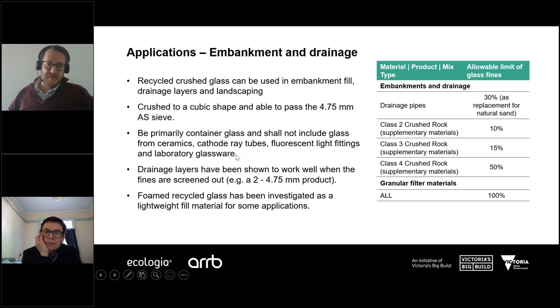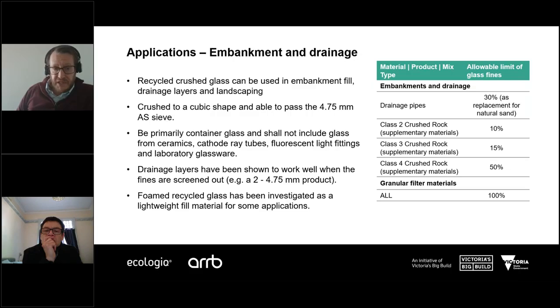Again, we need to be mindful of the source of our glass product. So we don't want to include any glass from ceramics or cathode ray tubes or fluorescent light fittings or even laboratory glassware. So that's again down to potential contaminants and the issues around leachates. Another interesting use of recycled crushed glass that's been highlighted recently is that there's the potential to produce a foamed recycled crushed glass product, which has some potential as a lightweight fill material for certain embankment applications.